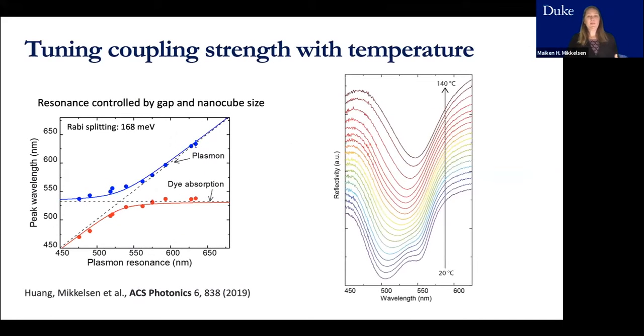We also varied the gap size and the nanocube size here to map out this anti-crossing behavior. So the dashed horizontal line here is the dye absorption, and then we are varying the plasmon resonance, and then we can see this double peak emerging here, and this characteristic anti-crossing. What we found was that we can actually also actively tune these structures in and out of this strong coupling regime, which I think is pretty cool.